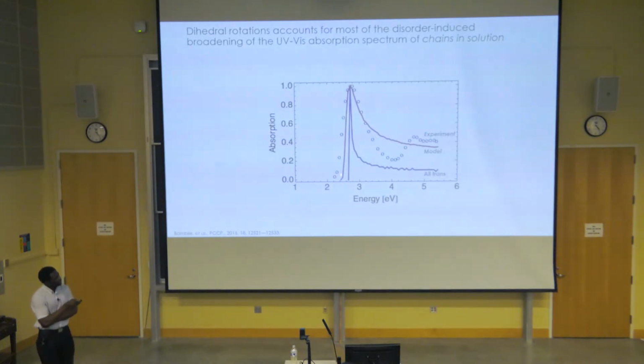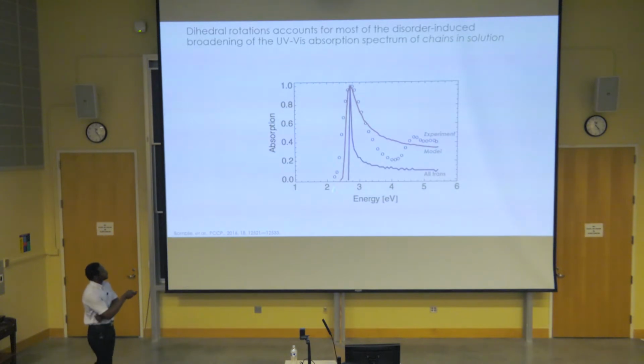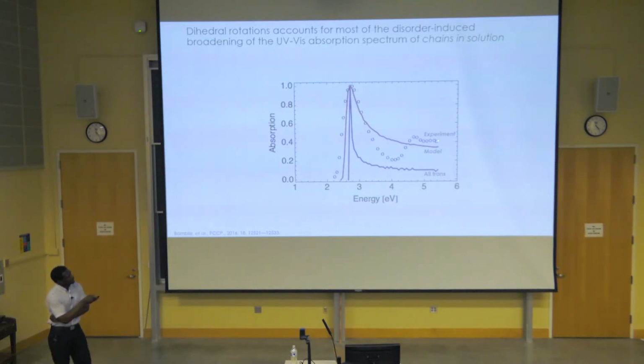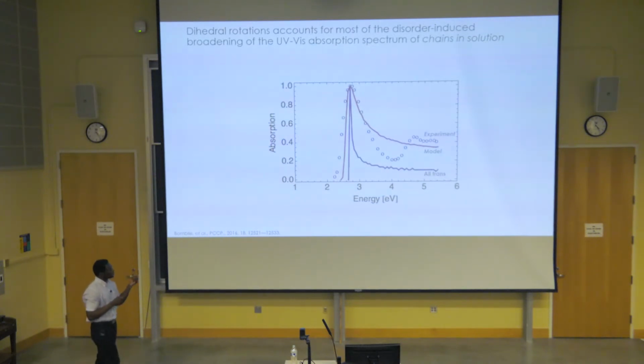So we've done that for an all-trans chain, so that is a perfectly ordered chain. And what we see is the absorption peak is very narrow. And when we did that for chains in solution, and here we have averaged this absorption spectrum over a large number of configurations of the chains, what we observe is that simply by taking into account the dihedral disorder, we are almost reproducing the entire broadening of the absorption spectrum that experiment reveals. And this only highlights that dihedral disorder alone plays a significant role in impacting the electronic properties of a polymer chain.